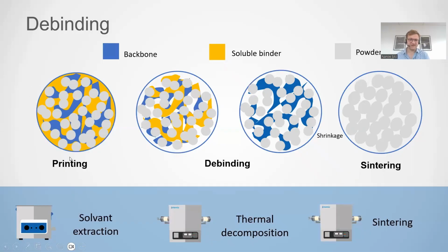Then we go through debinding. So we have a part, here symbolized with that circle, which is just printed, so you still have the powder and the different binders in it. And now you need to get from this to a final part, which is in ceramic or in metal. How do you do that? The first step is to dip the part in a solvent, which will remove approximately half of the binder.